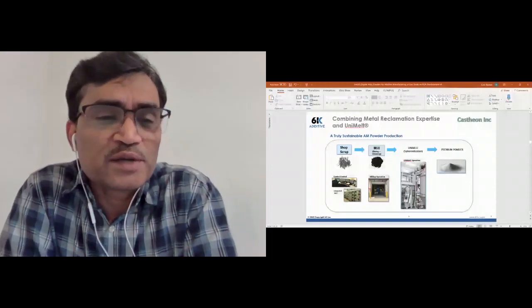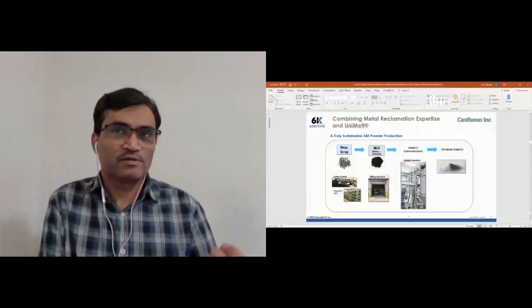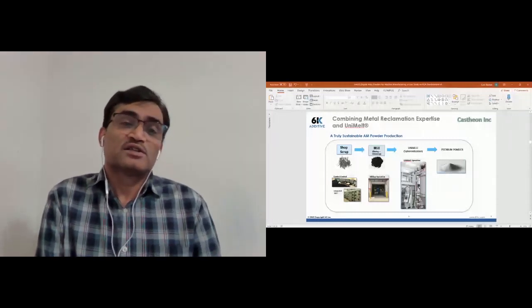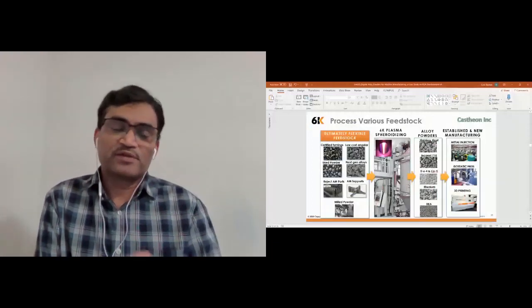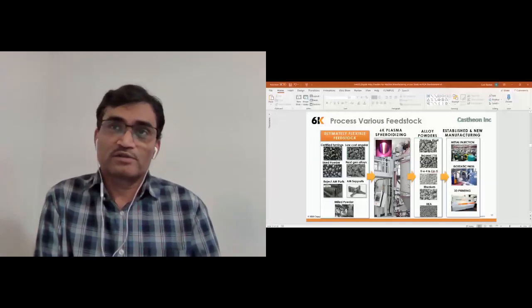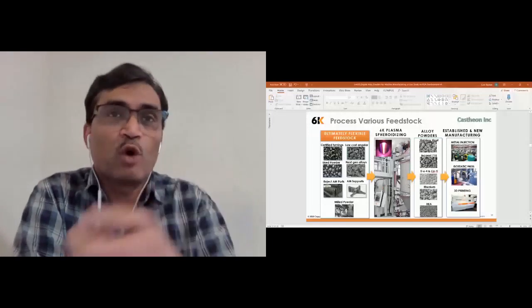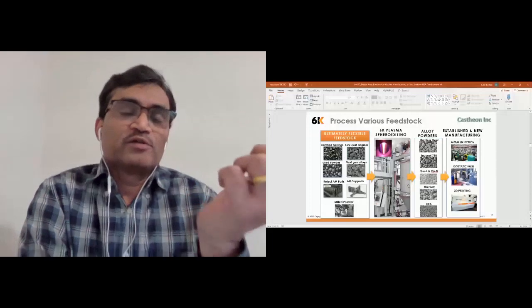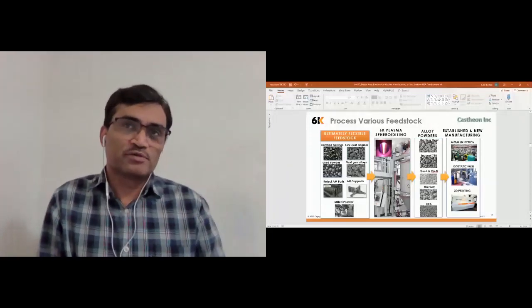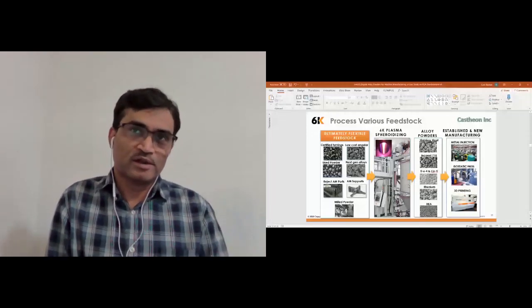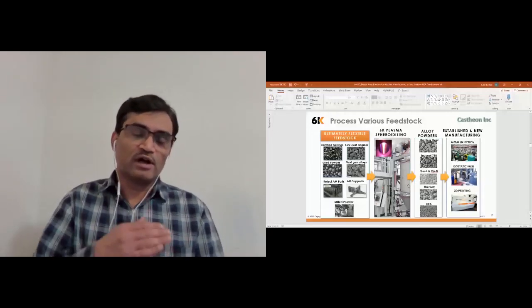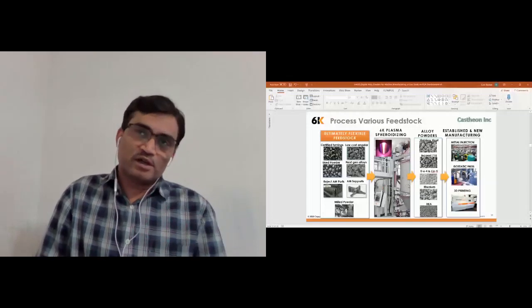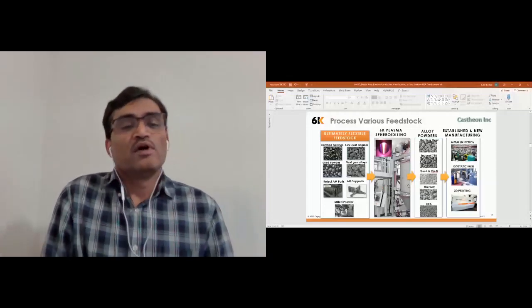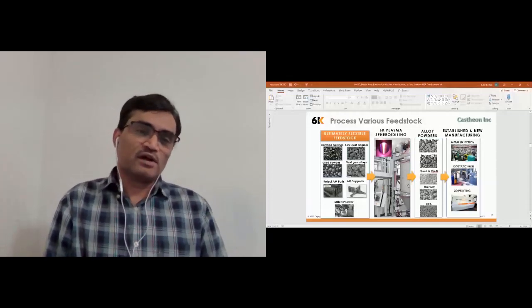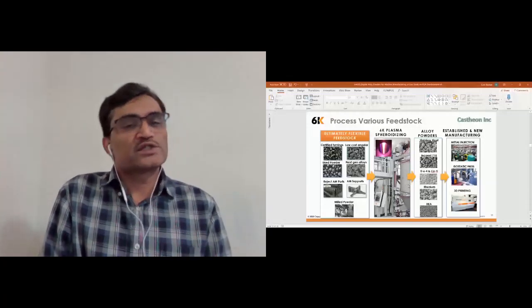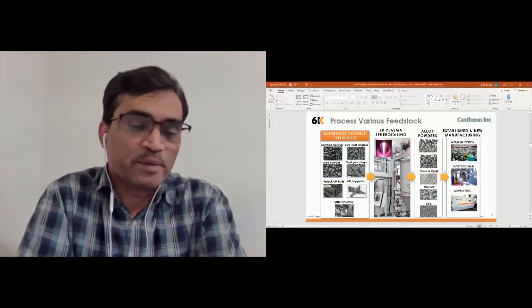And our system is very versatile. It can use different types of feedstock materials, right from shop turnings to low-cost angular powders made from different technologies. We can use used powders from additive manufacturing machines, which become less spherical or contain more satellite particles and are no longer useful. In most cases, it increases oxygen. In one of the presentations from Carpenter, we have seen how increased oxygen content affects the powder quality. In that case, it was titanium 6-4. But we have demonstrated that we can use higher oxygen powder and reduce it in our plasma to get the oxygen to acceptable levels.